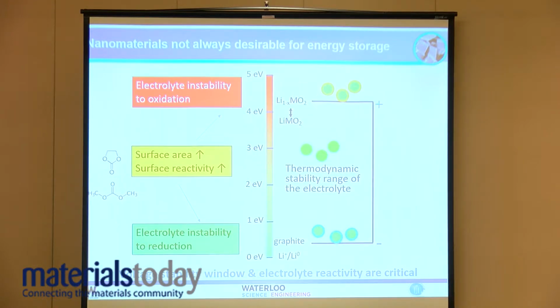So the point is that at the positive end of that electrode, the electrolyte, as I mentioned before, is unstable to oxidation. And the reason these materials work at all is because they have a passivating coating on the surface, which is carefully designed. And at the graphite, or negative, the carbon end, the negative side, there's also electrolyte instability or reduction. So effectively, batteries work not because of thermodynamics, because there's serious problems at both sides, but simply because of kinetics.